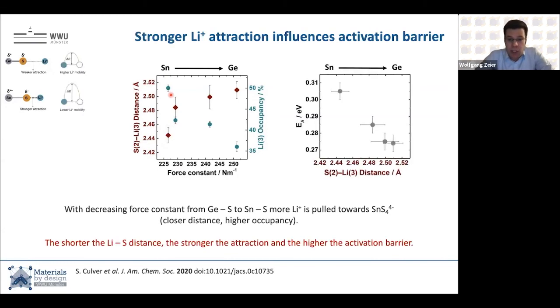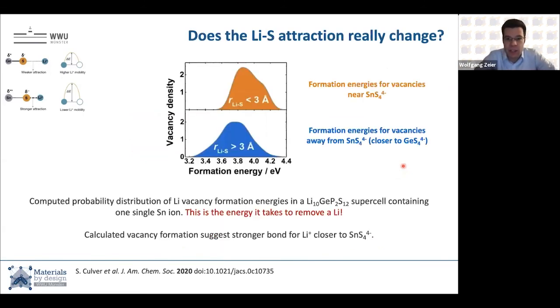How does the transport change? Well, we can plot our measured activation barriers versus this distance. And this shows us that the longer the distance is, the weaker the bond, the less energy we need to put into the system to make the ion jump from one side to the next one. But these are really just correlations. Is there really a causal change?